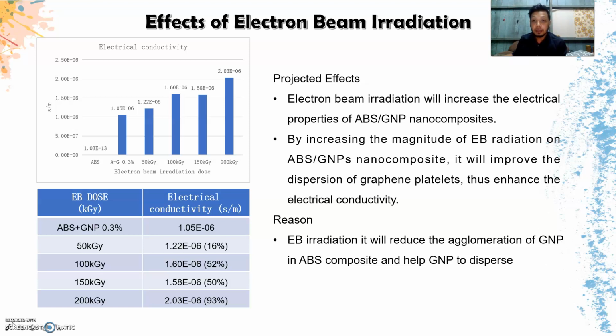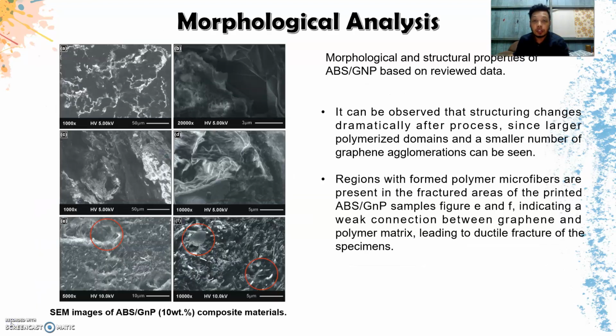By increasing the magnitude of EB radiation on the ABS/GNP nanocomposite, it will improve the dispersion of the graphene platelets, thus enhance the electrical conductivity. Reason: EB irradiation will reduce the agglomeration of GNP in the ABS composite and help GNP to disperse. For morphological analysis, these are the morphological and structural properties of ABS based on review data.